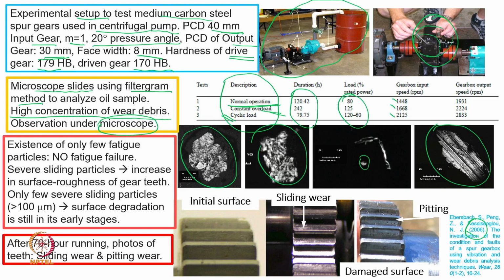Now, from this figure, what they could conclude is that there is no existence of many fatigue particles; only a few particles have the fatigue features. So they concluded there is no fatigue failure; even though there is cyclic loading, they do not find fatigue failure dominating there. However, they operated this only for 70 hours. It is not that they operated for 200 hours; what I showed in the previous slide was about 98 hours, while in this case they operated for 70 hours.